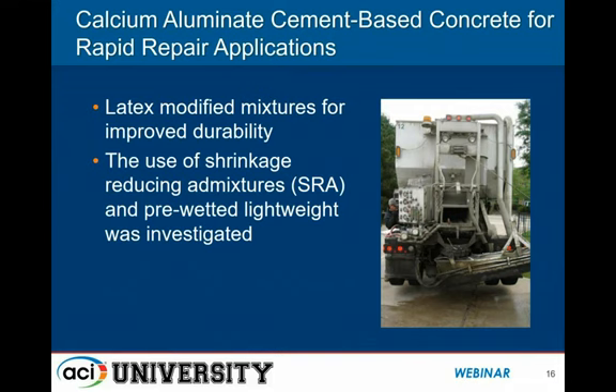So we set out from the very beginning to address this. And one of the things we did was look at a latex additive. Another strategy we used was to try to mitigate shrinkage with both shrinkage reducing admixtures and pre-wetted lightweight aggregate. And these are both strategies that have gained a lot of attention lately, in the last 5 years or so.